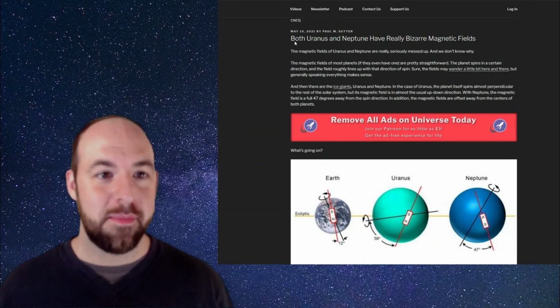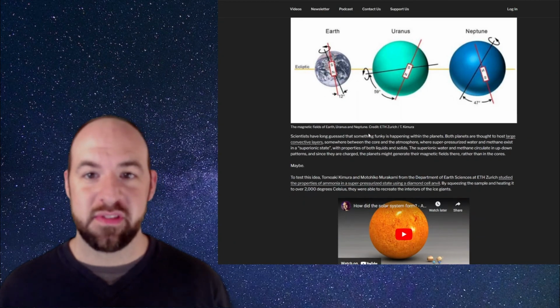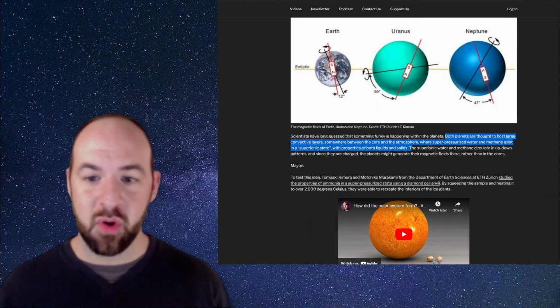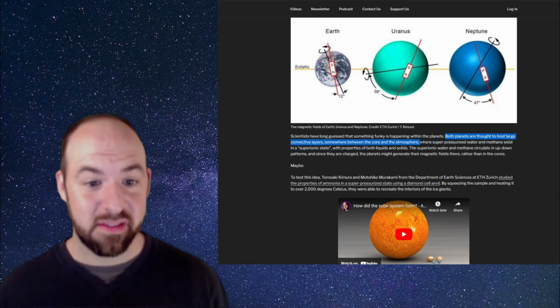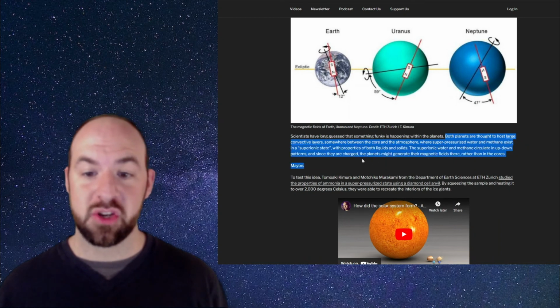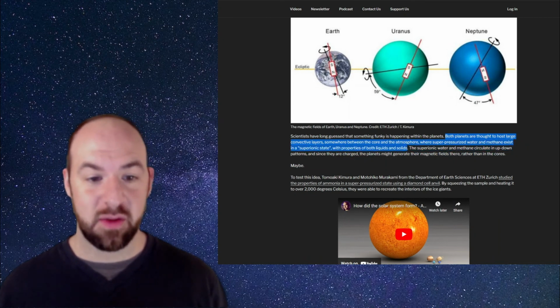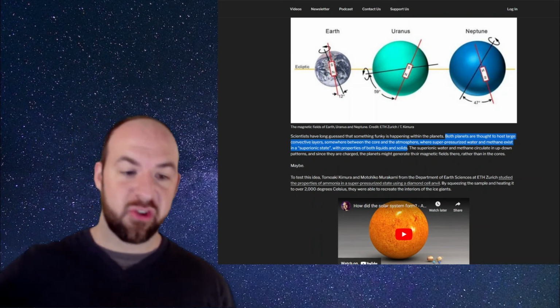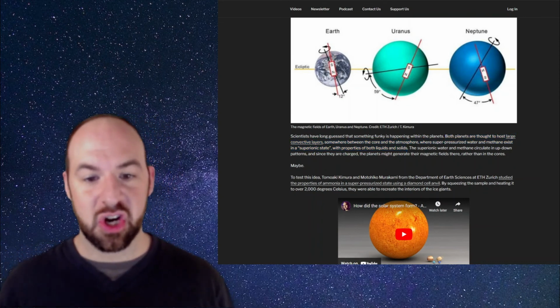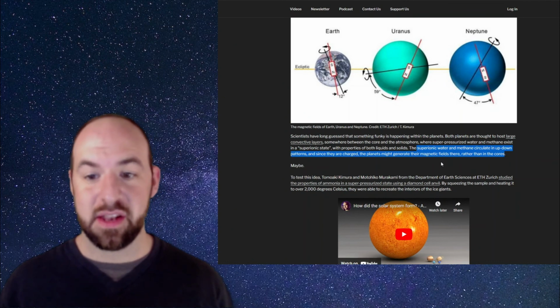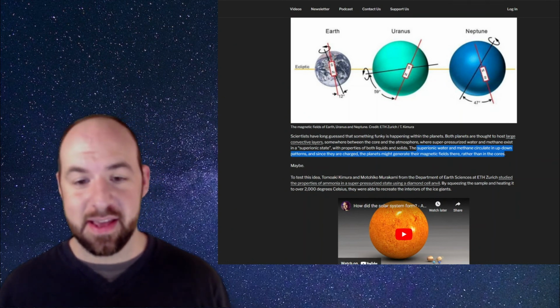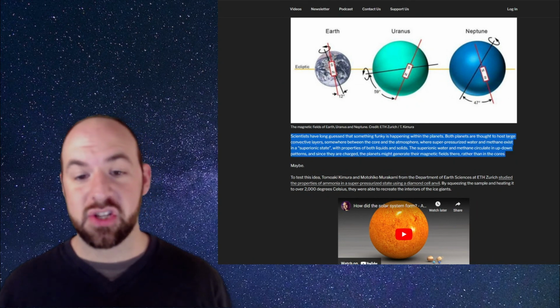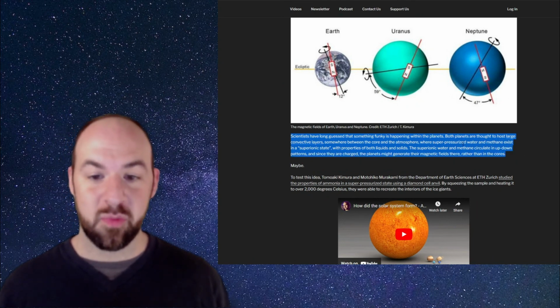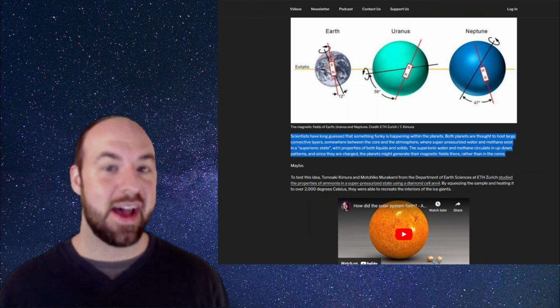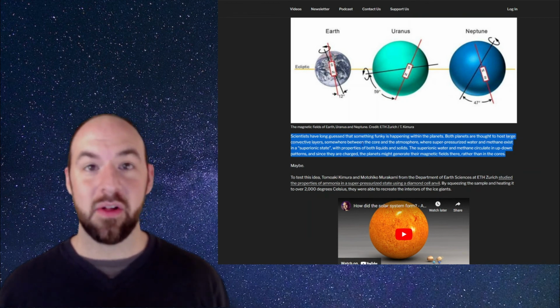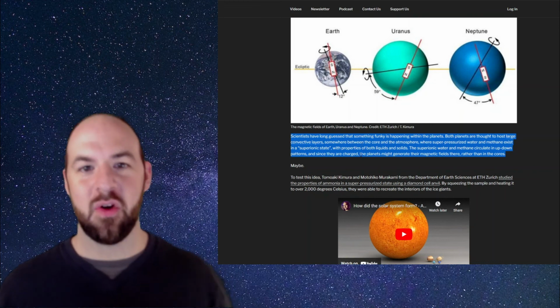So going back to the paper that talks about how both Uranus and Neptune have really bizarre magnetic fields, it does confirm this idea. They say that both planets are thought to host large convective layers, somewhere between the core and atmosphere, where superpressurized water and methane exist in a superionic state with properties of both liquids and solids, and it's circulating in up and down patterns, and since they're charged, the planets might generate their magnetic fields there rather than the cores. And what this paper that we read today is doing is saying, well, actually with this diamond formation, not only would you have the superpressurized water and methane, but you could have metallic hydrogen in there as well, which could be a potent contributor to this overall magnetic effect.